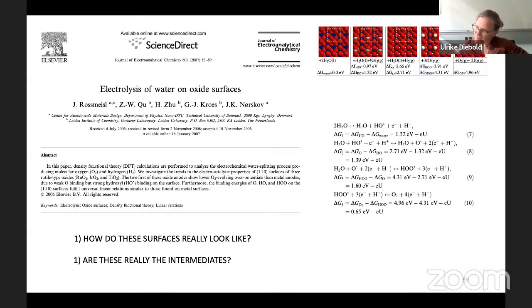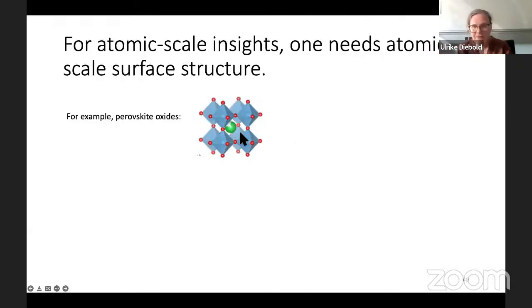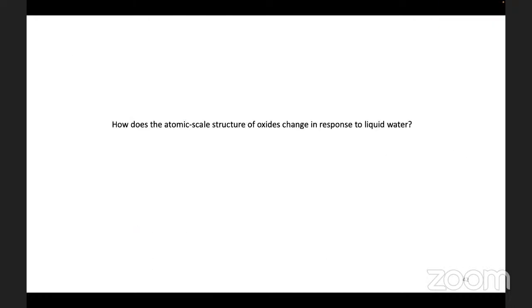I can tell you if they're stable or not, and then you can look at different oxygen chemical potentials, pressures and temperatures. But for very simple surfaces, there's a good chance that they are. For something that looks simple, like perovskite oxides, I can definitely tell you they will not be AO or TiO2 terminated. I can tell you it will not be the case. So for the perovskite, for sure, it has nothing to do with reality. That I can tell you. Okay, thank you. All right, good.